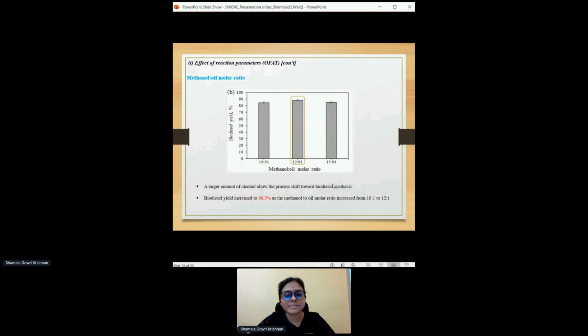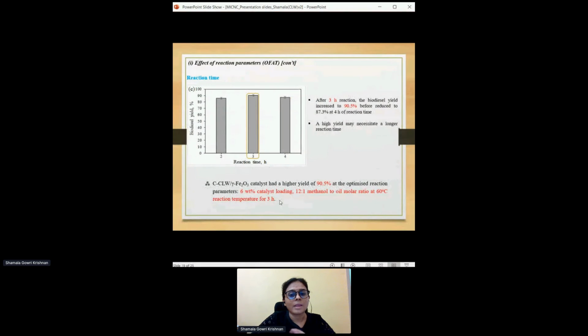The second parameter is the methanol to oil molar ratio, where we found the highest yield was achieved at the 12 to 1 methanol to oil molar ratio, with 88.3%. Lastly is the effect of the reaction time, where we found the 3 hours reaction was the best reaction to produce the highest yield of